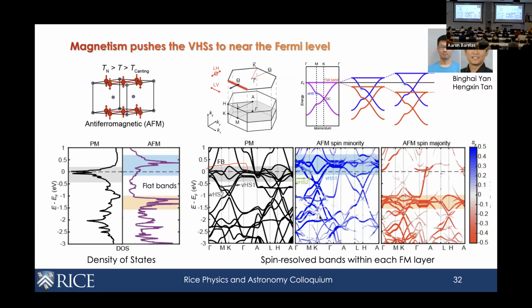One of the issues that always comes up with strange metals, things that are not Fermi liquids, is what the relationship is between the electron lifetime and the transport lifetime. So is there a line width you can try to extract to tell you the electron lifetime? Yes, this is a very good question. No, we cannot. The problem is that with three-dimensional materials it's very hard to cleave, so it's already very hard to actually resolve the dispersive bands. So the width is not a pure measurement of the intrinsic lifetime. But that's a good point.